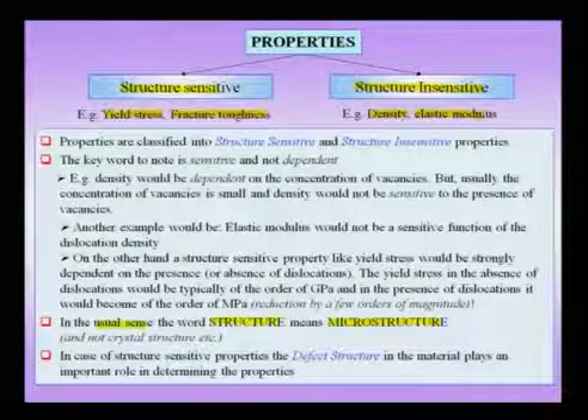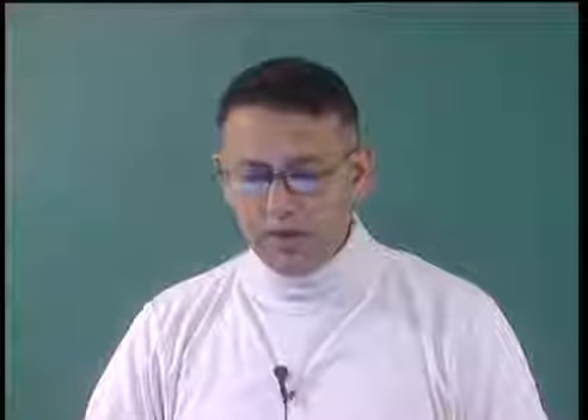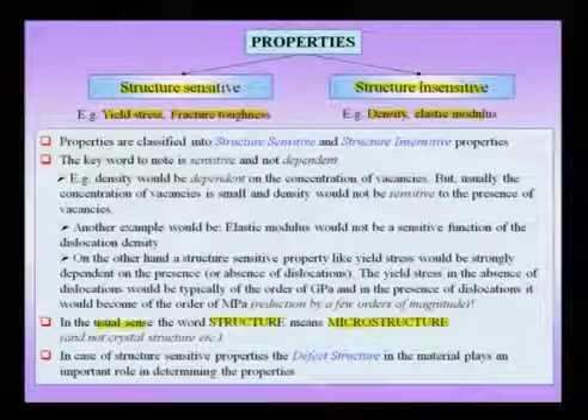The key word in this definition is the word sensitive. Here we are not using the word dependent, but the word sensitive. For instance, the presence of point defects in a material would affect the density in a small way. Therefore, the density would be dependent on the presence of vacancies in a crystal, but it is not going to be a sensitive function of the presence of vacancies. On the other hand, the yield stress of a material could be a sensitive function of the presence of vacancies, and therefore, we have to worry about whether properties are structure sensitive or structure insensitive. And to once again reiterate, when we use the word structure sensitive, it usually means microstructure sensitive properties.